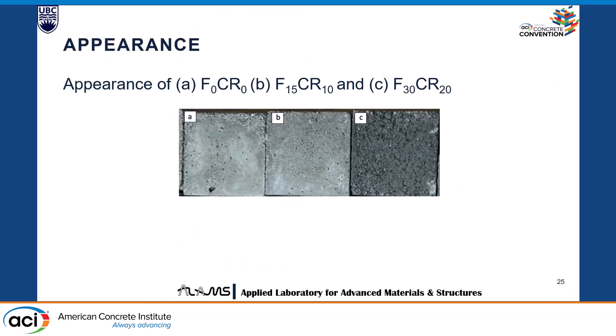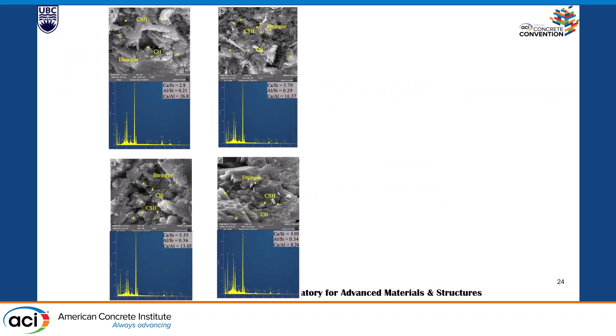You can also see the appearance of the wood ash based mortars. The ash sample was very dark — almost black — and the mortar color became darker with increasing ash content. From the SEM of the mortars, we observed a gradual increase of wood fly ash in the mortar corresponding to a gradual decrease in C-S-H and an increase in calcium hydroxide compared to the control concrete.